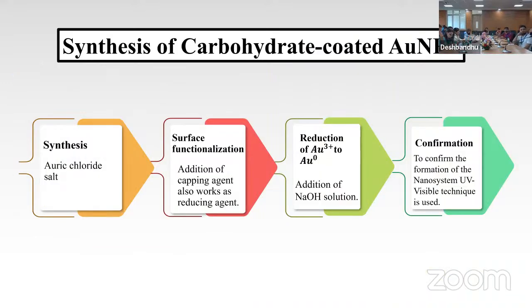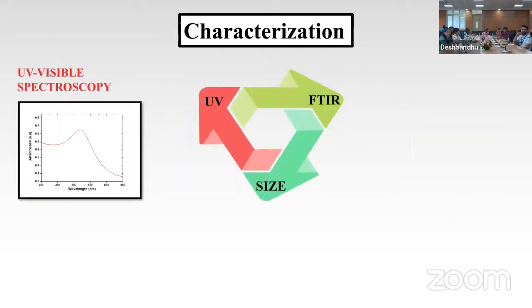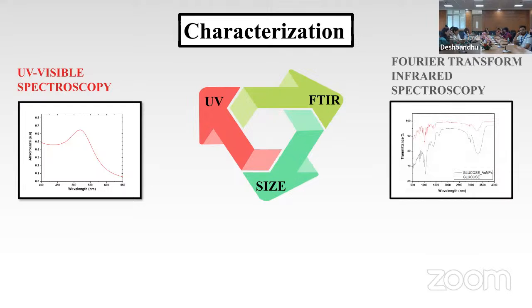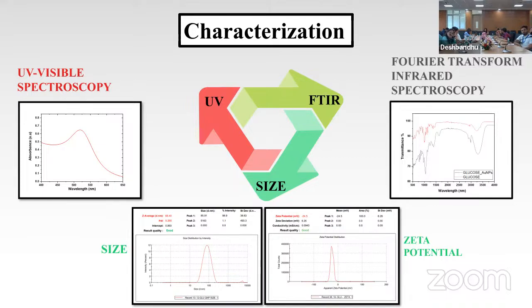The chemical reduction method was performed to synthesize the various carbohydrate-coated gold nanoparticles. In this synthesis, the carbohydrate behaves as both a capping and a reducing agent, and UV-visible spectroscopy is used to confirm the formation of the nanosystem. Characterization was done by UV-visible spectroscopy, IR spectroscopy and dynamic light scattering. The absorption spectra showed a peak at around 540 nanometers, confirming synthesis. IR spectroscopy analyzed the capping; a shift in the peaks confirmed successful capping of the carbohydrate on the nanoparticle surface. The stability of the colloidal solution was analyzed by zeta potential, and the size makes the nanoparticles useful for targeted drug delivery because they can reach the target site easily and minimize side effects.